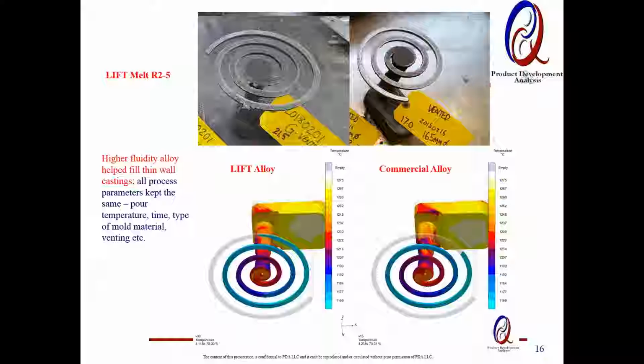So this is out of our melt R25 that we developed to make thin wall ductile iron castings, high fluidity alloy that helped us fill successfully thin wall castings. And here is an example of experimental work, just a simple spiral fluidity spiral, which is quite popular.